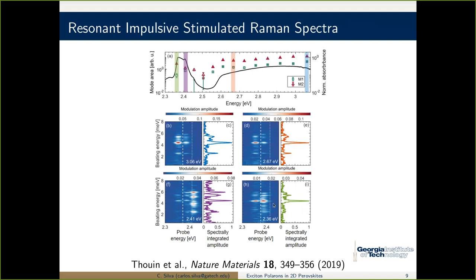And of course you've got hot excitons here, less hot excitons, you've got hot carriers here, less hot carriers, and there is dissipation, and you see hot carrier relaxation dynamics. But the resonance Raman spectrum that I measure by pumping higher in energy or lower in energy seems to be the same. So the electron-phonon coupling that drives the relaxation dynamics is already imprinted in whichever way you pump. That would be my answer.